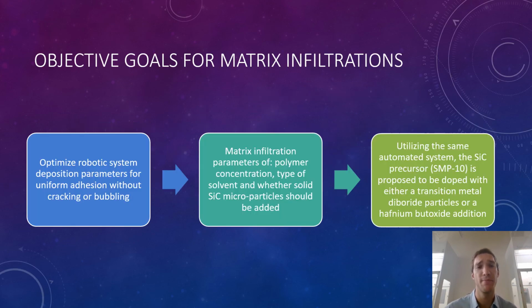Now, focusing on the first bullet point, it breaks down into three objectives for looking at the buildup via PDCs of this matrix for the CMC. We're looking at optimizing the robotic system deposition parameters to look for uniform adhesion, but without any cracking or bubbling in the matrix, very important. We're also going to be looking at matrix infiltration parameters: polymer concentration, polymer type, as well as the type of solvent, and whether or not silicon carbide microparticles should be added to control the porosity and thus permeability of the CMC.